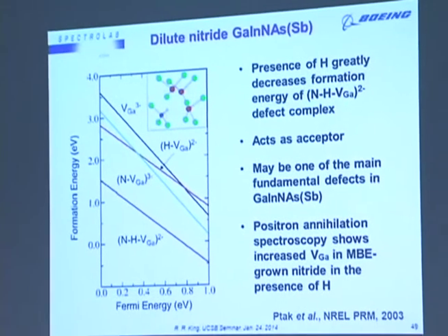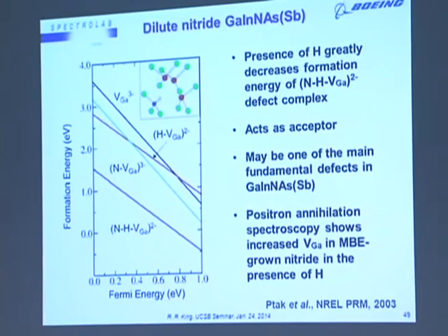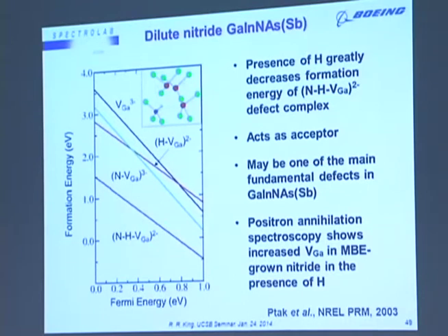In terms of the identity of the defect that's formed in gallium indium nitride arsenide, one very interesting result from modeling is that the presence of hydrogen greatly decreases the formation energy of this defect complex, this nitrogen-hydrogen gallium vacancy defect complex. So you can see the formation energy is way down here. So when you have hydrogen around, this defect is fairly easy to form.